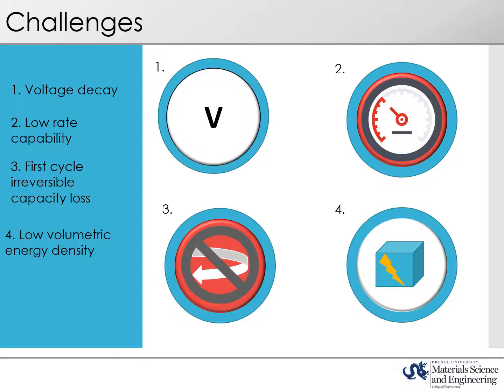Finally, low volumetric energy density, caused by a combination of voltage decay that insinuates the gradual structural transformation of the LLO material to a spinel-like phase, capacity fade that leads to the TM dissolution and structural transformation to the spinel-like phase, and often small particle size, which has higher surface area, causes an increased reactivity with electrolyte, a thicker SEI layer, and increased oxygen loss.